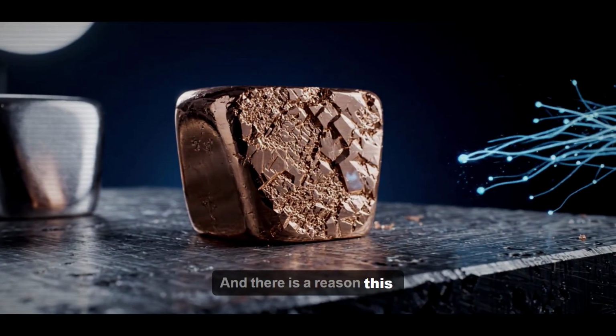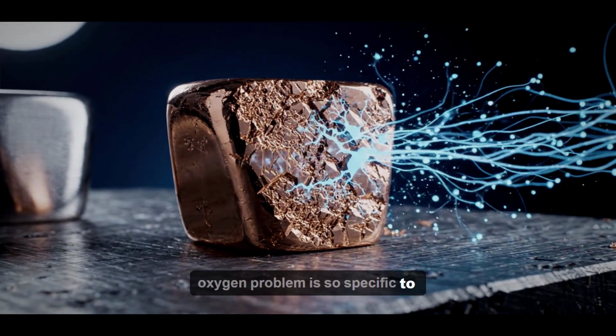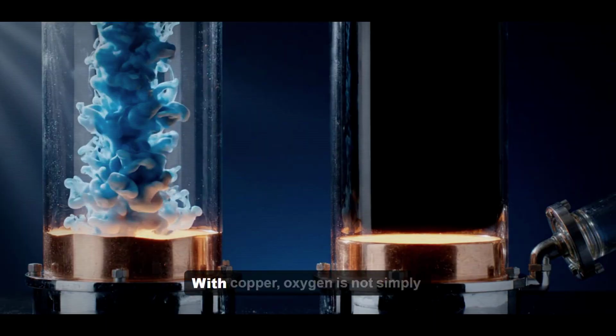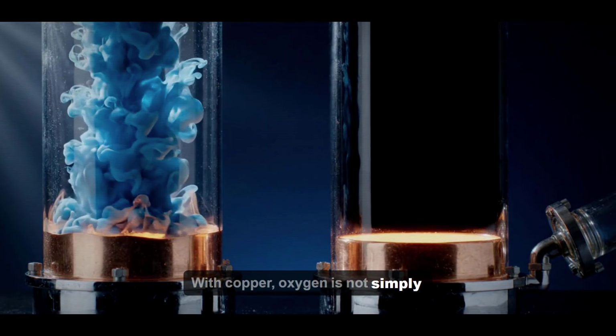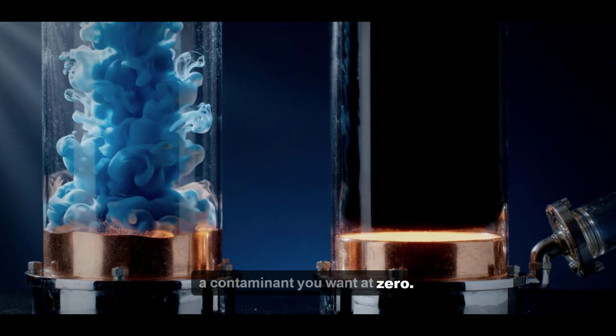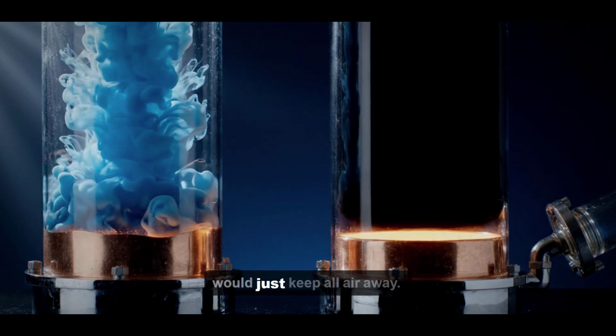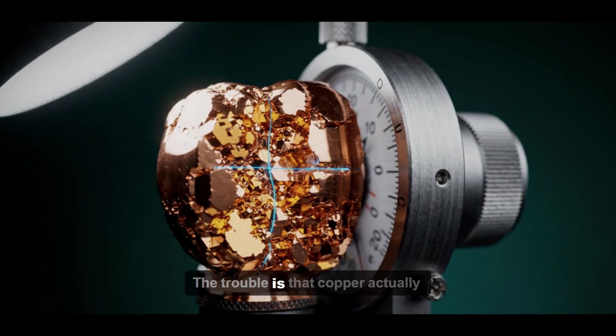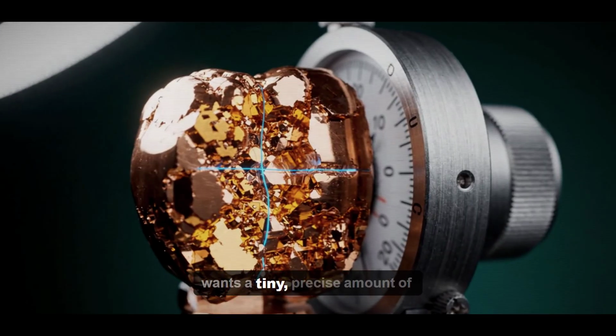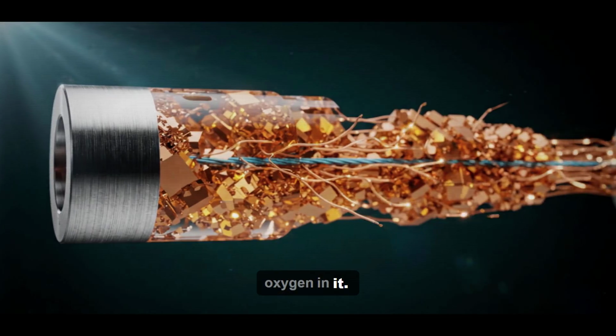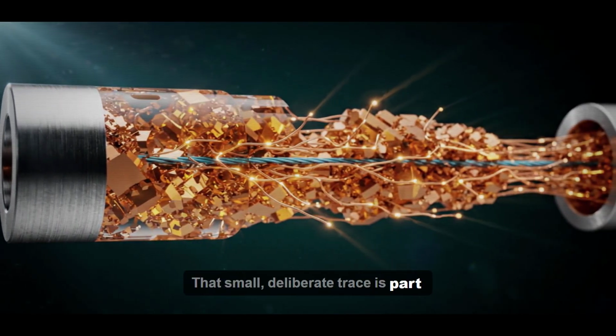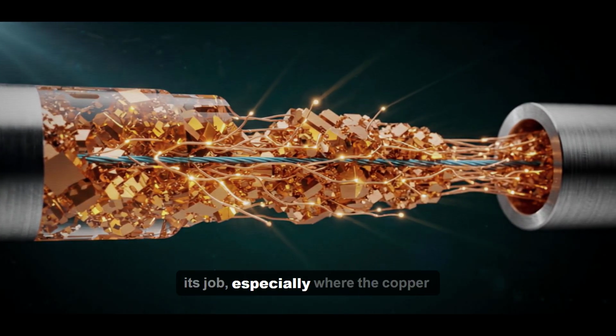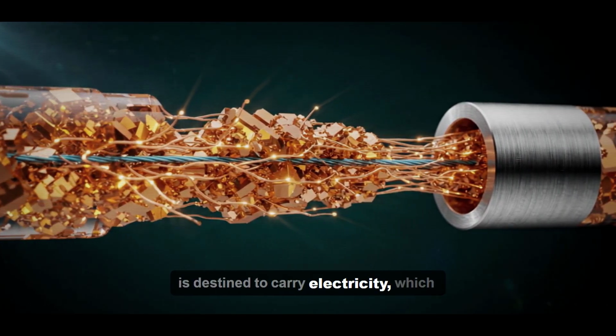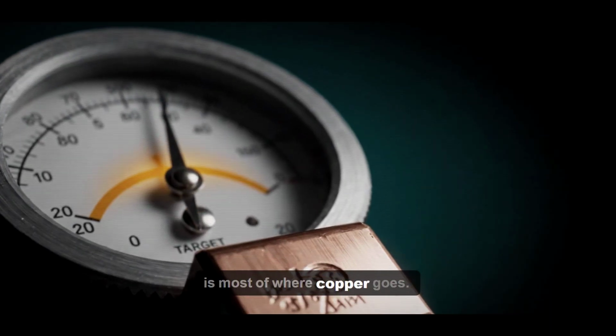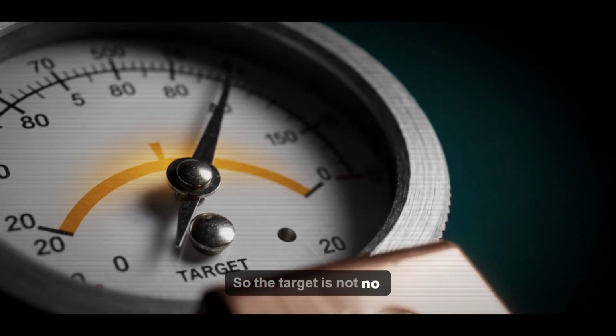And there is a reason this oxygen problem is so specific to copper and so unforgiving. With copper, oxygen is not simply a contaminant you want at zero. That would almost be easier, you would just keep all air away. The trouble is that copper actually wants a tiny, precise amount of oxygen in it. That small, deliberate trace is part of what makes the metal do its job, especially where the copper is destined to carry electricity, which is most of where copper goes. So the target is not no oxygen.